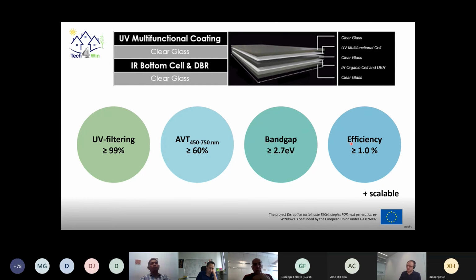Ideally, we believe we can go for efficiencies even to 2.5% on the long term. However, at this moment, our short-term target is to aim for 1%. As you will see, we're getting close, and hopefully we get very soon this 1% so that we can move on to the next step. And all of this is scalable. So the sizes, the areas Alejandro already mentioned a few presentations ago, we are currently upscaling this device already up to 5 by 5 square centimeter, and we probably even have to go a bit larger.